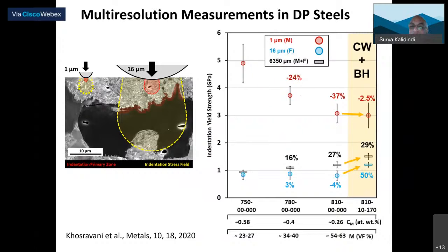So in this particular case, we are looking at processing of these DP steels. The first set of numbers is the annealing temperature. The second set of numbers is the deformation. After annealing, you deform it by 10% in this case, a rolling reduction. And then you're doing a 170 degrees bake hardening in this particular case. So, of course, we can do as many as we want.